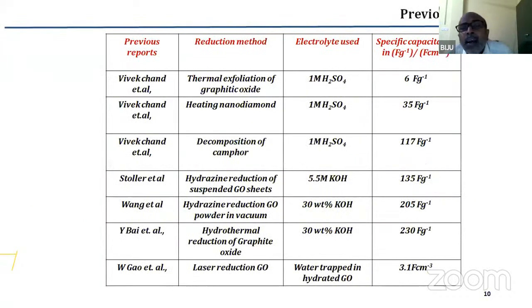You can see that H2SO4, then KOH, all these things have been used as electrolytes, whereas graphite oxide and reduced graphite oxide are used as the active materials. And you get specific capacitance values. Specific capacitance means capacitance you could obtain per unit mass of the active material.